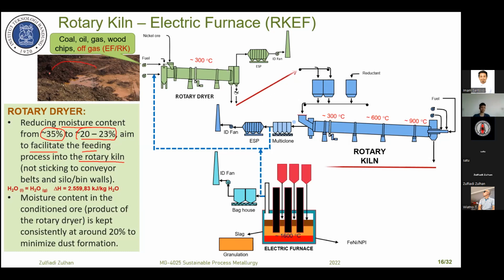If you see this, the common laterite nickel ore, if there's rain, the water content could in this case be more than 40%. And the nickel ore, if you see in this case, will adhere or stick on the conveyor. If we transfer this wet nickel ore directly without drying into the rotary kiln, we can save energy for sure. But this nickel ore will adhere or stick on the surface of the silo or on the surface of the bin. We cannot charge the ore from the bin onto the conveyor. It's very difficult because it sticks directly onto the surface.